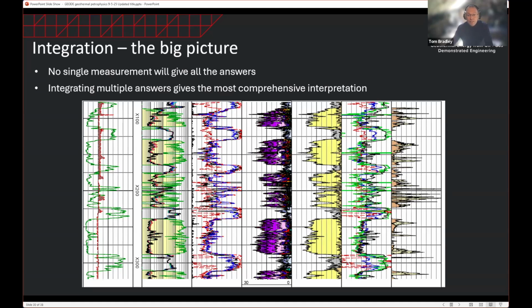Looking at our porosity distribution for the NMR data, you can see here we've got lots of large pores, therefore a very high quality reservoir. Even interesting things looking at our resistivity data by looking at the difference between shallow and deep measurements. We can see here we have an invasion profile, again telling us we have permeability. So really, don't look at one measurement on its own, get the big picture, look at all the information together. By integrating all these logs, it gives the big picture and the full comprehensive interpretation of your formation.